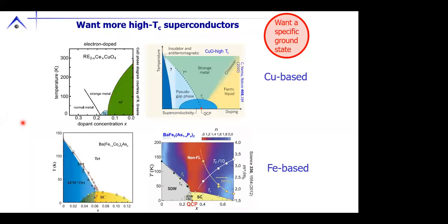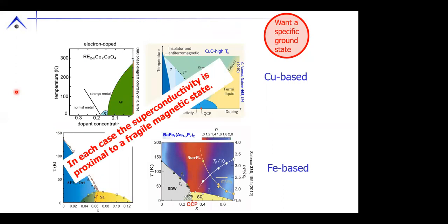So let's look at some of the classical families of high TCs. We can look at the cuprates and the iron-based materials, and our superconductivity in each of these cases is proximal to or intersected by a clashing antiferromagnetic ordering, okay? Now, we can then refine our desire. So we can say that in each case, superconductivity is proximal to a fragile magnetic state, okay? A state that we've suppressed to zero, and even as we've suppressed it to zero, in many cases, we see a reduction in the size of the ordered moment, okay?